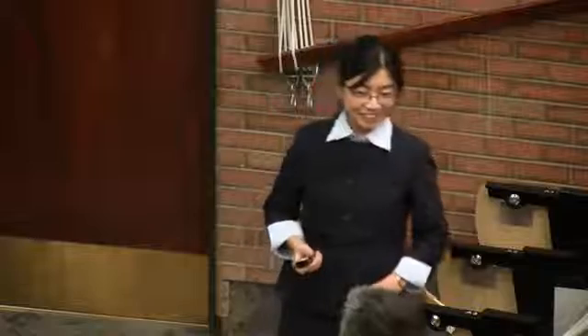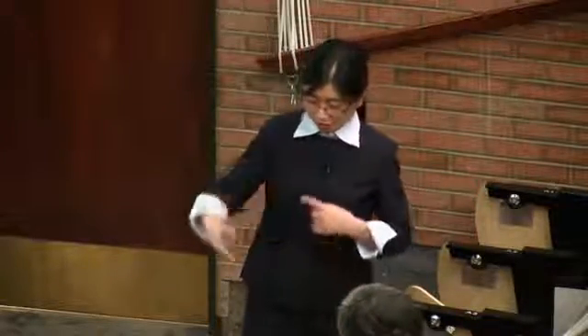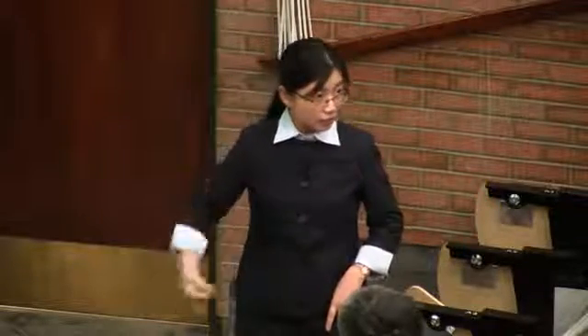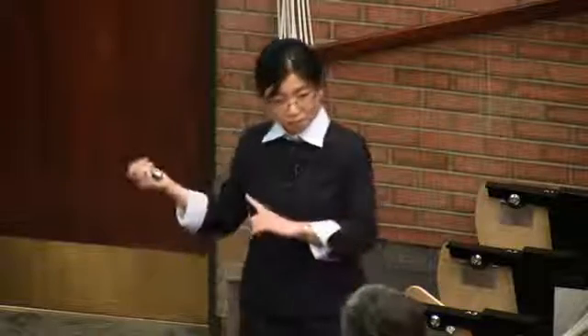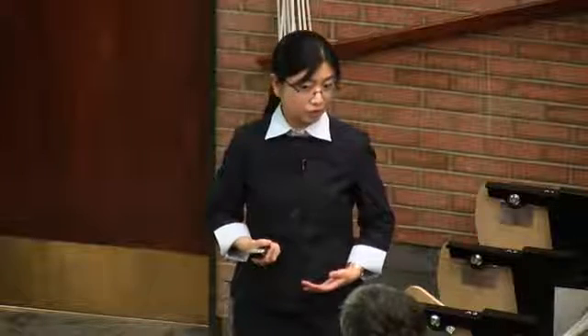So on a polycrystalline sample, it doesn't work? Polycrystalline still works. That's what's amazing here. Usually my impression is that spin precession in semiconductors works on high vacuum grown epitaxial films. But this material at first looked to me like it doesn't look very clean. Are we going to get a signal? But it works surprisingly well.